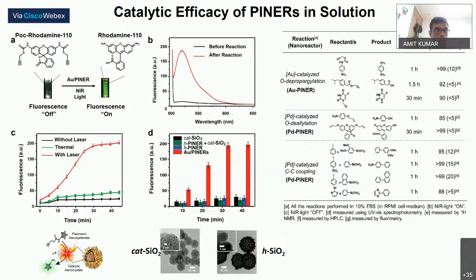In the absence of laser, we don't see any conversion within this time frame. And when the reaction is heated thermally to around 40 degrees Celsius, we see very poor conversion. This clearly shows that this reaction can be selectively carried out by NIR laser irradiation. We also performed several control experiments to prove that this interfacing of plasmonic and catalytic components is very crucial for the function of the nanoreactor.